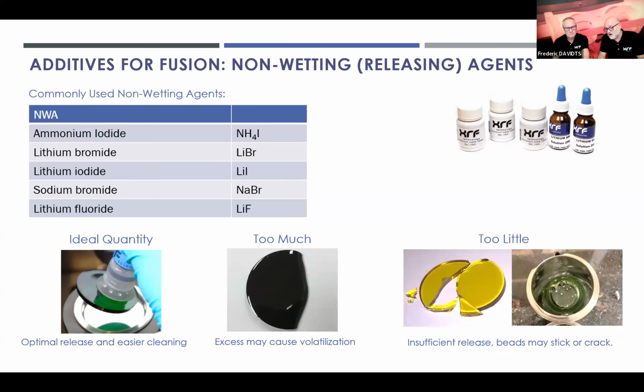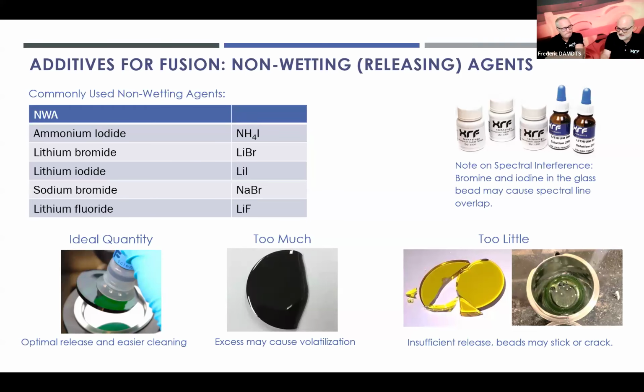And if you put no non-wetting agent or just a little, then you can have the beads cracking, or you can have the material sticking in the bottom of the crucible. I would say there is an interference effect by adding iodide or bromide, and you need to be aware of that. But of course, if you use the same flux for the calibration and for your routine analysis, the effect is compensated. But really, using a non-wetting agent helps for the day-to-day work, because it's easier to clean the crucible and to release the beads. So we definitely recommend using a non-wetting agent.